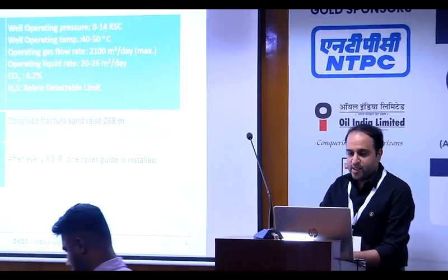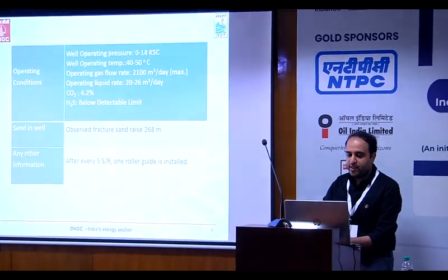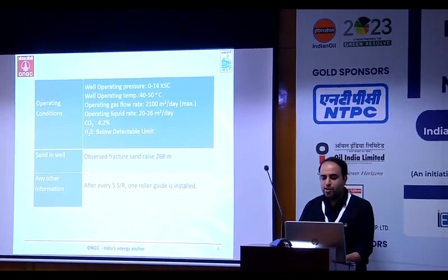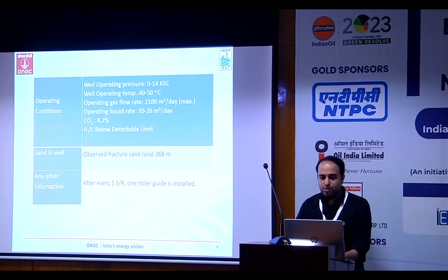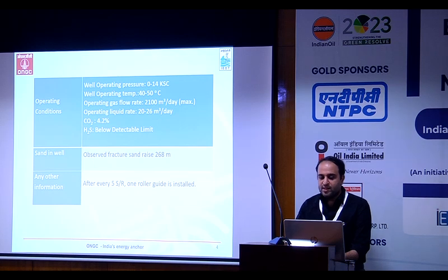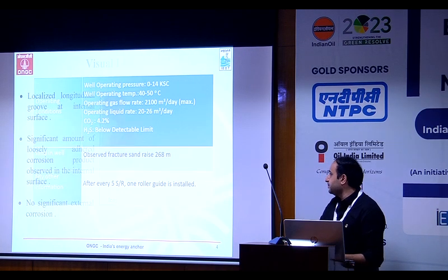Apart from these are the operational data. The well operating pressure was 14 kg/cm². The temperature was around 40 to 50 degrees. There was CO2 around 4%, but no H2S was observed. Apart from that, sand was also observed in this tubing.